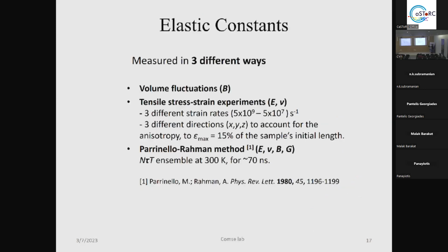Afterwards, we will calculate the elasticity of the system in 3 different ways. Again, we did it in 3 different ways in order to decrease the error bars because of the small size of the system. With volume fluctuations, with tensile stress-strain experiments, and this with 3 different strain rates and 3 different directions in order to take out the errors as far as possible, and with the Parrinello-Rahman method.